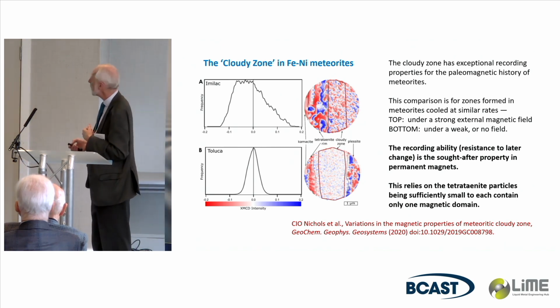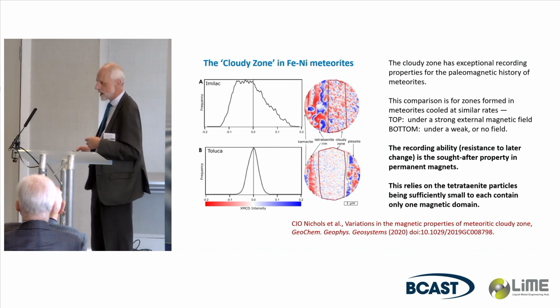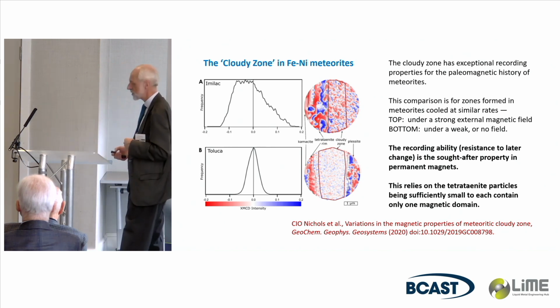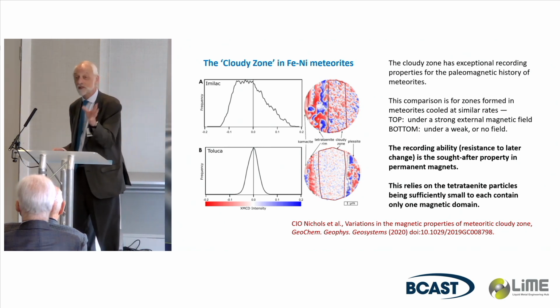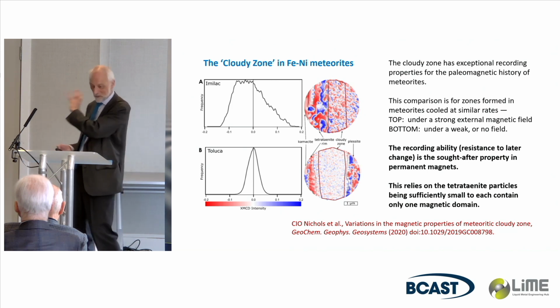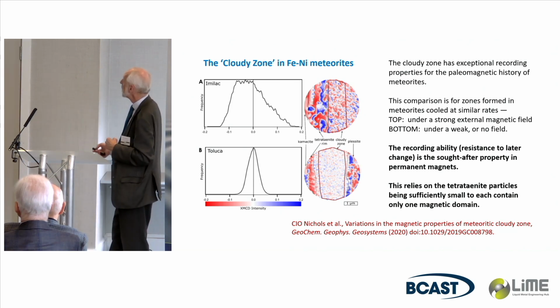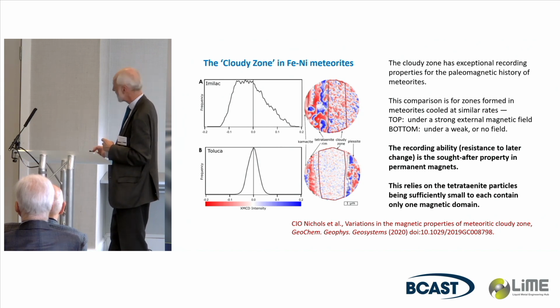Because it turns out from the meteorite world, there's the zone called the cloudy zone. It's relatively rare, has a rather special microstructure. I should say not all meteorites are iron nickel, but this is a family of meteorites. And this zone turns out to be of great interest because it has a magnetic recording ability.